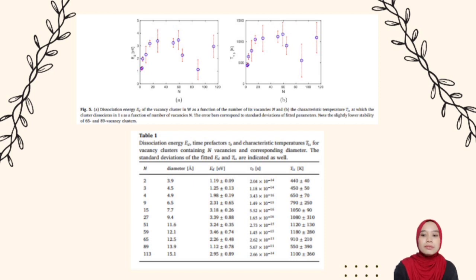This corresponds well to a decrease in the density of vacancy clusters after 1 hour annealing at 800 degrees Celsius observed by positron annihilation spectroscopy (PAS). The created voids are not the most thermally stable voids, and this is the start of void dissociation, not the complete void.